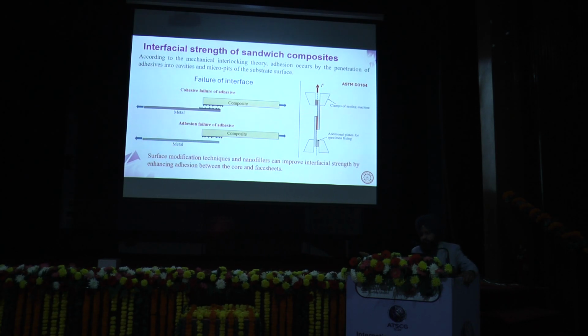The interfacial strength of sandwich panels is the most important part. This layer is basically the intermediate between your core and metal. It has two failure modes. One can be cohesive failure, in which the adhesive itself fails, and then there may be adhesion failure, where the bonding fails, particularly with metal face sheets. This is mainly due to oxide layer formation on the aluminium face sheets. We can characterize this by using lap shear strength, and the interfacial strength can be improved by surface modification on the aluminium face sheets, or by integrating nanofillers into the adhesives, or we can use both.